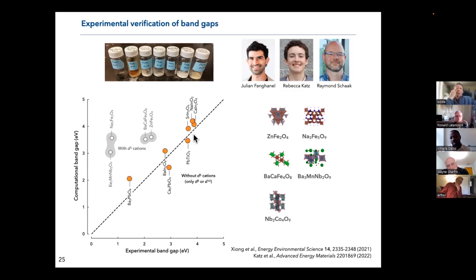And again, here, this does not affect significantly the outcome of our prediction because we're mostly interested in non-platinum group metals. We're not interested so much in transition metals, but more in main group metals, such as indium, such as lead, antimony, and this type of main group oxide. And so this provides a critical feedback that this method can serve well to predict the optical properties of main group oxide, but we need further work if we were to be interested in transition metal oxide.